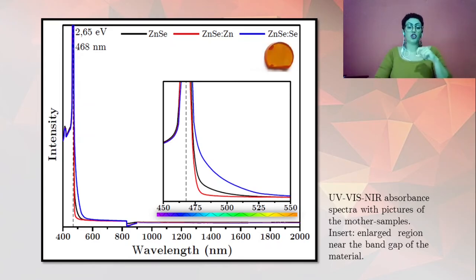The absorbance measurements show that the ZnSe Se sample has an enhanced absorbance in the blue to green spectral region, giving it a more orange color, while the sample ZnSe Zn has less absorbance at these wavelengths, giving it a more greenish color. The ZnSe sample, of intermediate color between the two others, also has an intermediate behavior for the increased absorbance close to the optical gap of the material.